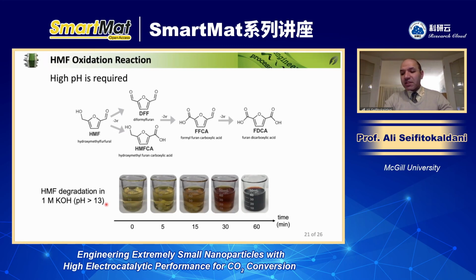But what we observe in the lab is just putting HMF inside the 1 molar KOH and just waiting. No applied potential, nothing. Just put the HMF inside the 1 molar KOH and wait. In 1 hour, you see what happens to the HMF. It starts being degraded, which you don't want. So that's a challenge. You don't want to really work with the HMF in alkaline environment. We have a few papers on that. We also work in alkaline environment, but this is the challenge that I would like to mention. So we need to be careful about it.